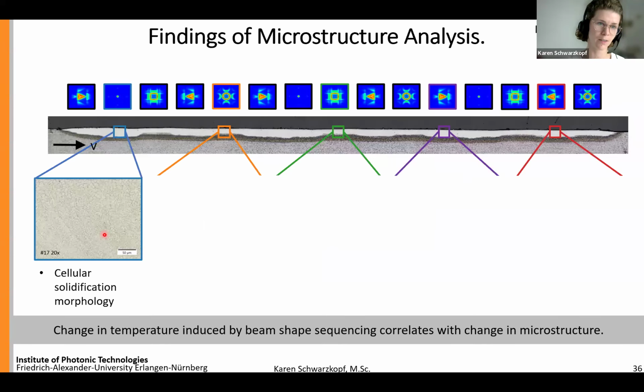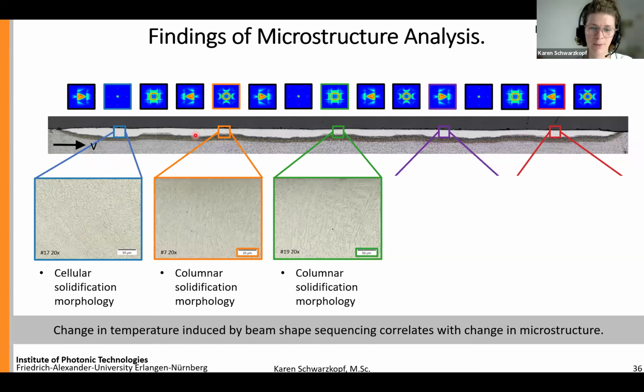All right. So for the point-like intensity distribution, we do see a cellular solidification morphology, or most likely a cellular solidification morphology. Whereas when we are now heading to the beam shapes that are exhibiting higher thermal or mean temperatures, we are getting columnar solidification morphologies. And this is really interesting again, because the differences that we could see in the temperature do really occur in our melt pool, in our microstructure as well.